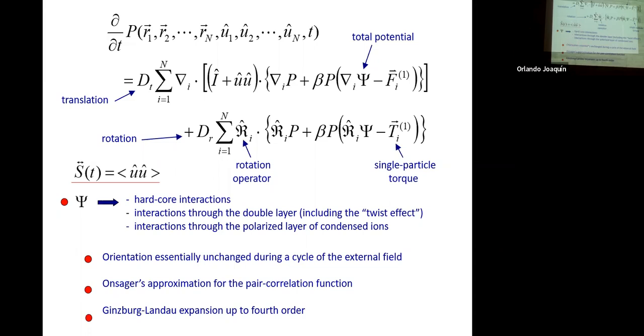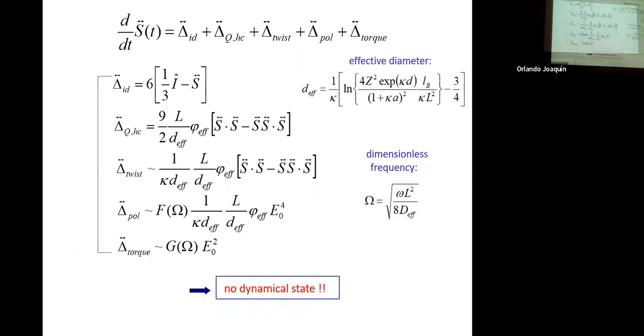Then you assume that the orientation of a rod hardly changes during the cycle of the electric field, which is the key. We use Onsager type of approximation for the correlation function, and you do a power series expansion to fourth order in the order parameter, in which you get this equation for the action.